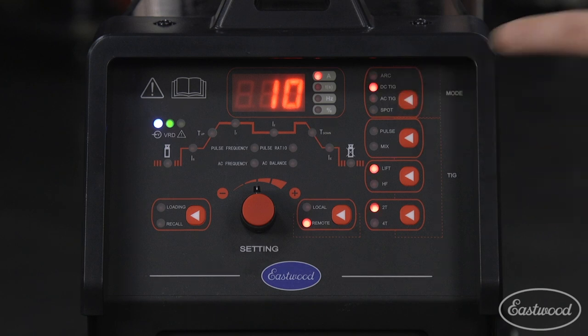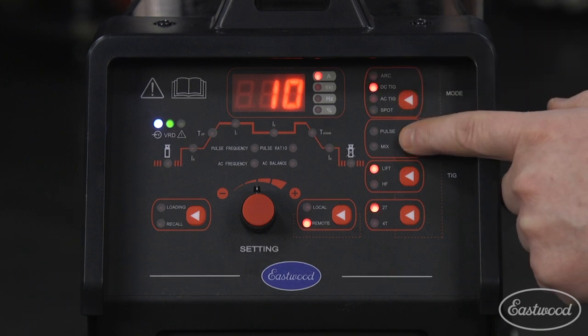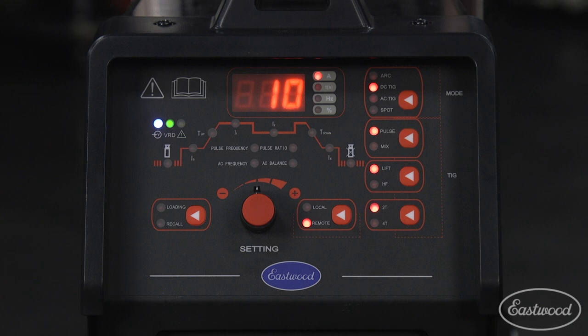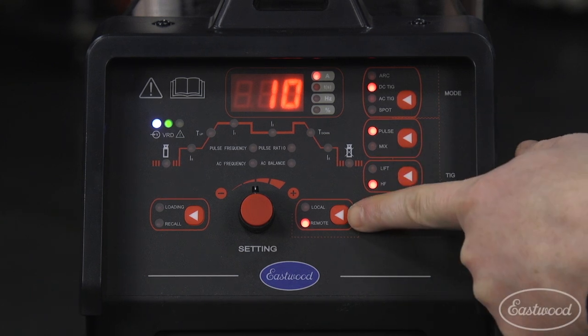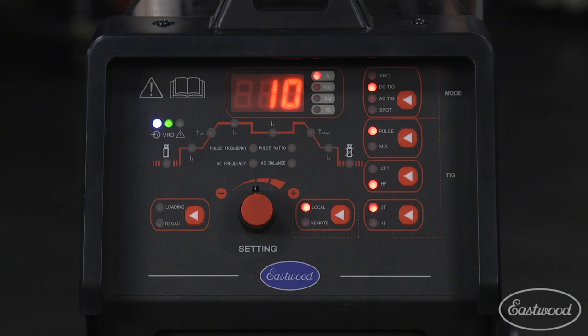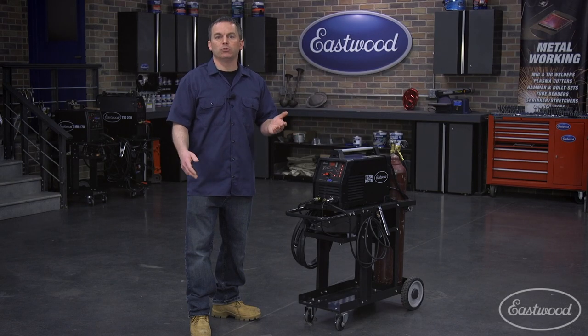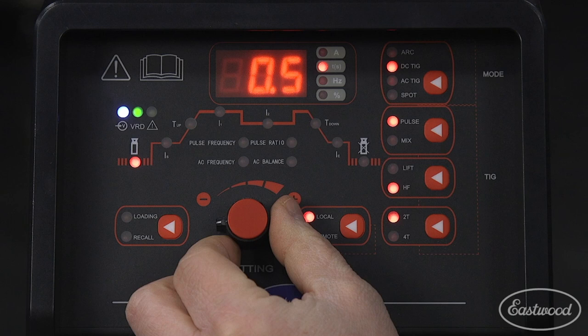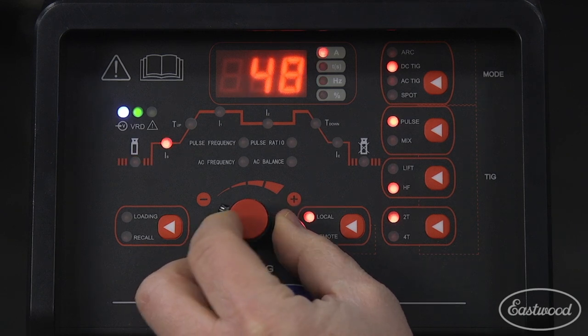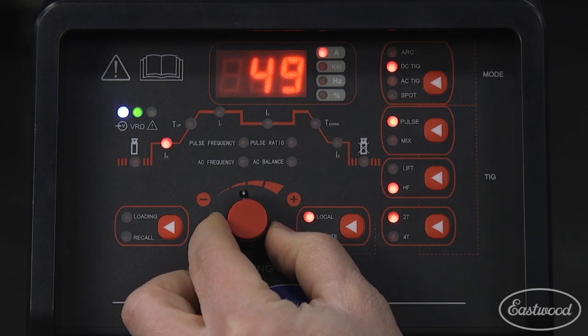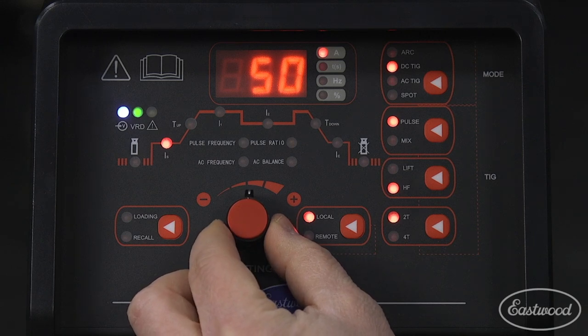To set DC pulse for welding steel, select DC TIG. Then select your other parameters. Select lift start or high frequency. Select local or remote, which is torch or foot pedal control. And we'll choose local to use the torch. Now set the preflow starting amperage, which we'll set to 50, and the upslope time, which we'll set to 0.